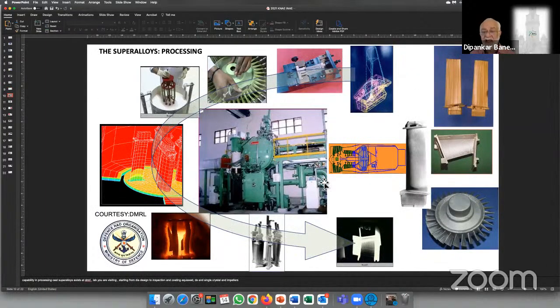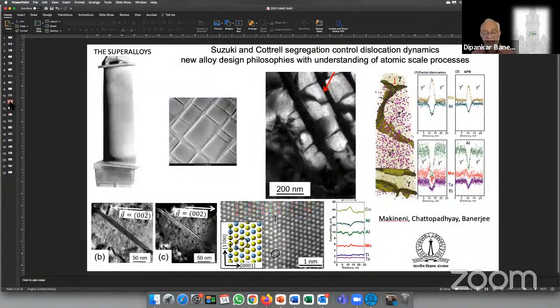The turbine materials are the most critical parts of the aero engine. And we have today both research and manufacturing capability of single crystal nickel-based material, directionally solidified nickel-based alloys, equiaxed components, or such integrally cast structures. The entire process, starting from die design to core manufacture and injection, because these blades are hollow, and then ceramic molding and the casting processes have been developed in our laboratories and are under production also at the Hindustan Aeronautics Limited. We support this manufacturing capability by materials research of such superalloys.